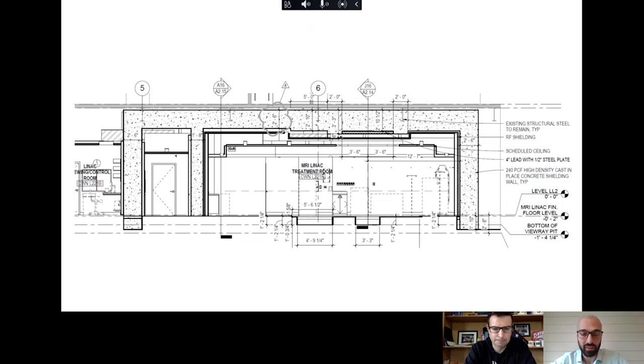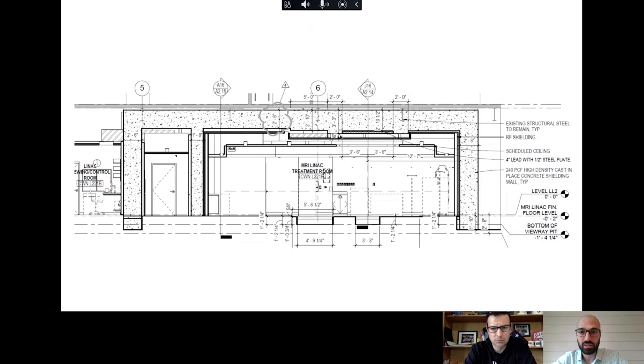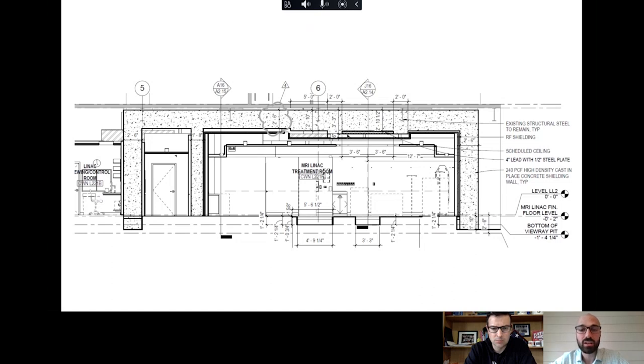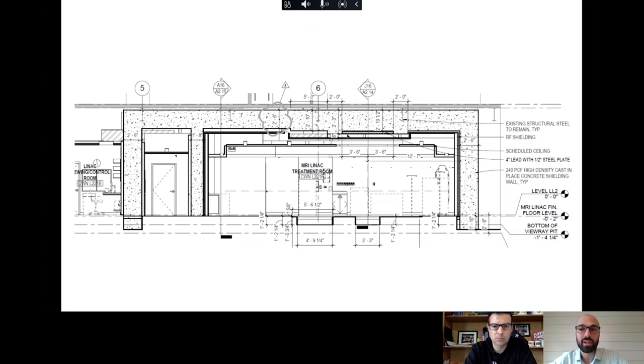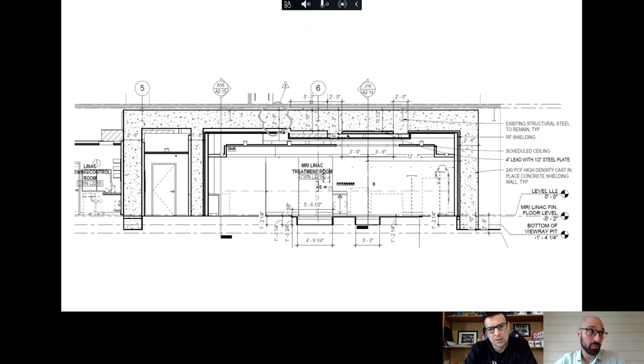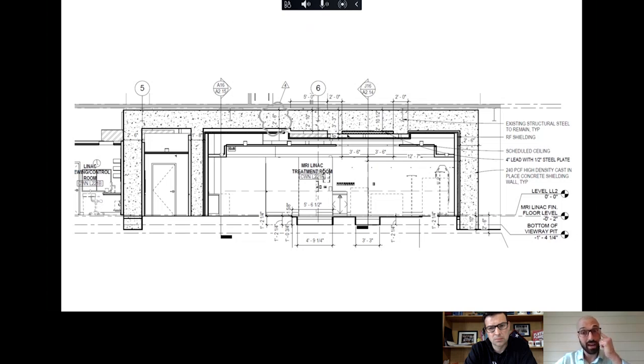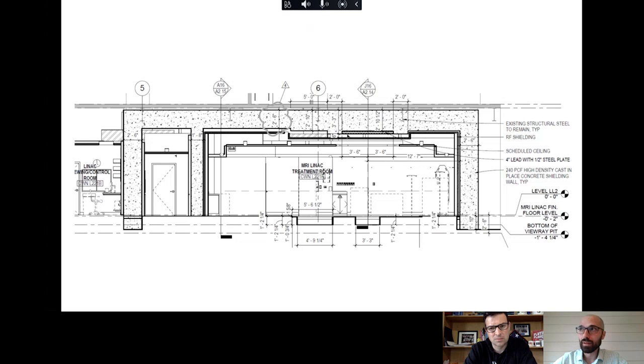So this was the final plan that we ended up with. We were able to embed some lead bricks in the underside of what they call the primary beam, where the radiation levels are highest. And that helped us to shrink the overall depth of this ceiling. But the majority of it ends up being 2'6 thick at 240 pounds a cubic foot. So we had Gary Miller from Nelco with us, and he was kind enough to share the sort of proprietary mix design that they use on their modular blocks. And we used that, this is where things really, you talked about construction junkies, this is like a concrete junkie endeavor.